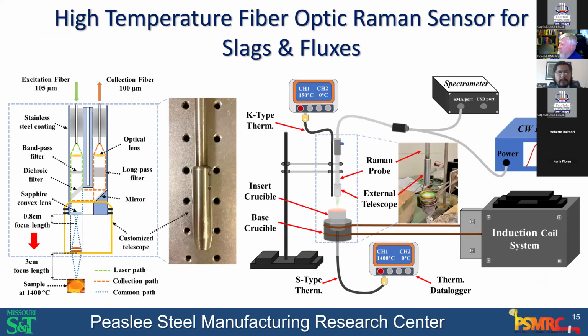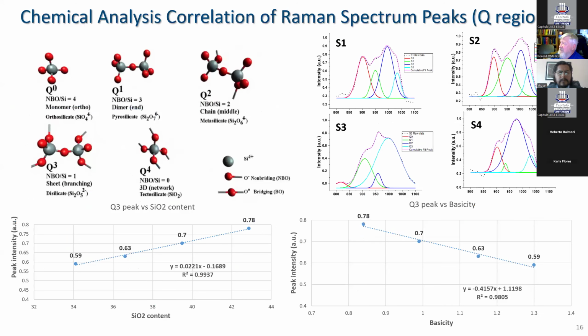Another area where we're doing sensing is in the area of high temperature Raman analysis for slag chemistry and structure detection. And we've built some high temperature Raman probes that are capable of delivering a laser excitation signal and then collecting the resultant Raman emissions from the slag. And we can do that at elevated temperatures.